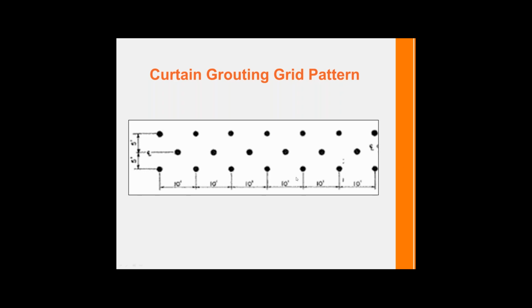Well, as we're pumping this first row at the bottom, that grout's starting to expand all through here. Now, why is that important? Because what we're doing is pumping, injecting, and creating what becomes a shelf, so that everything we pump after the fact in our next holes moving up in procession now has a shelf to sit on. They won't continue to settle down via gravity. They'll actually work their way left, right, and up, which is what we want.